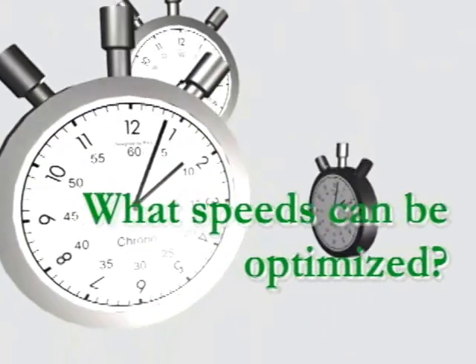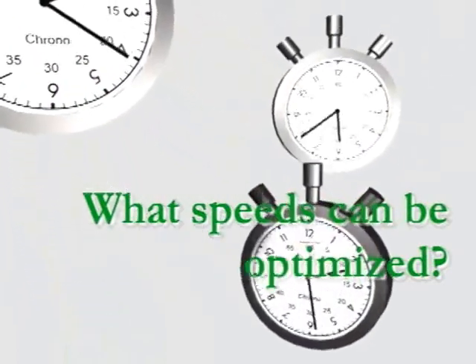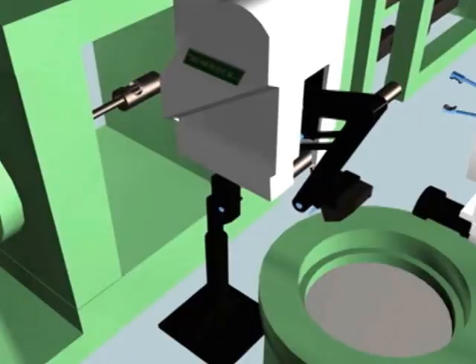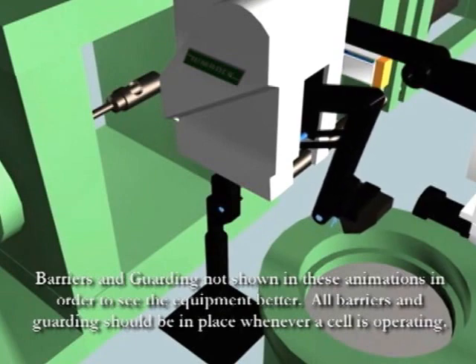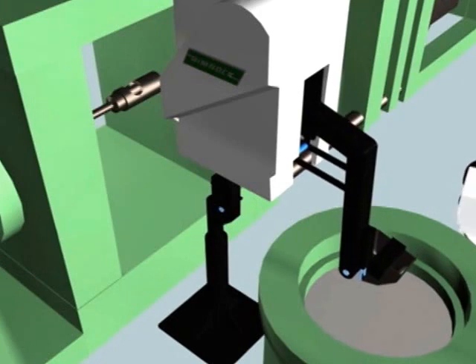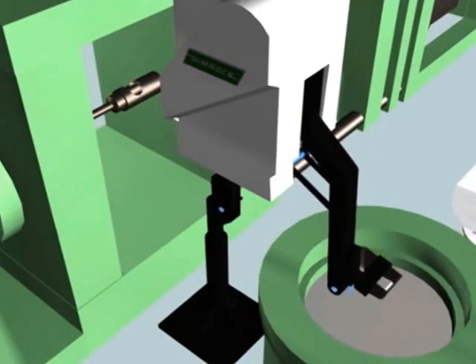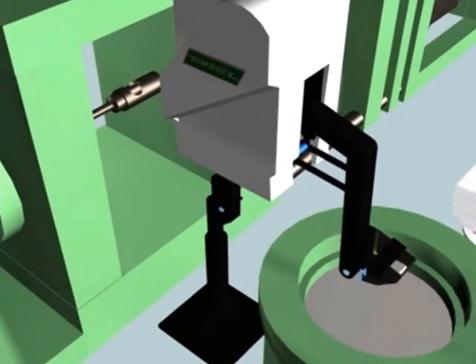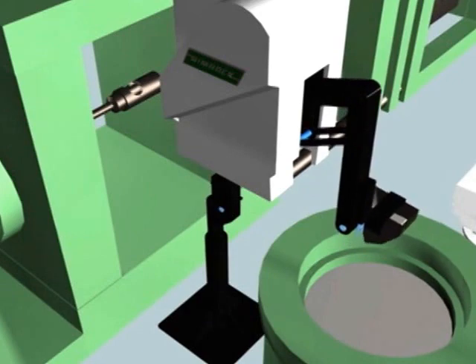What speeds can be optimized? It is not wise to set the speeds to their maximums if the ladle is going to wait for a start signal. Typically, most shops maximize the speed from the holding pot to the die-cast machine to prevent a loss in metal temperature.